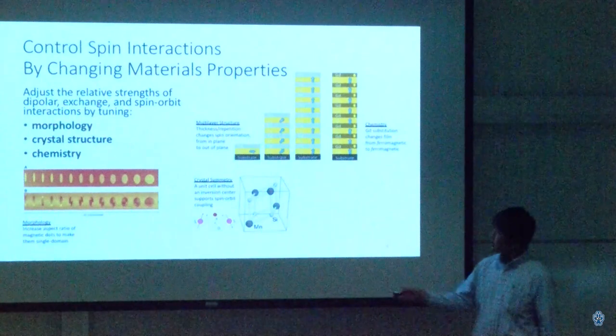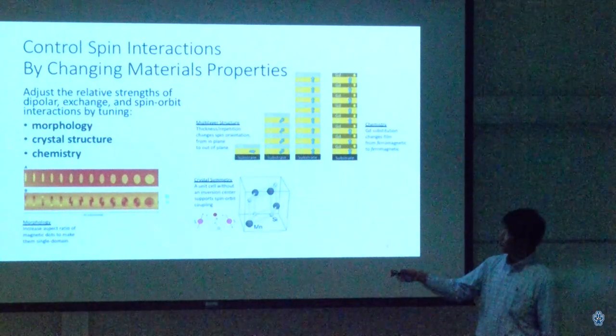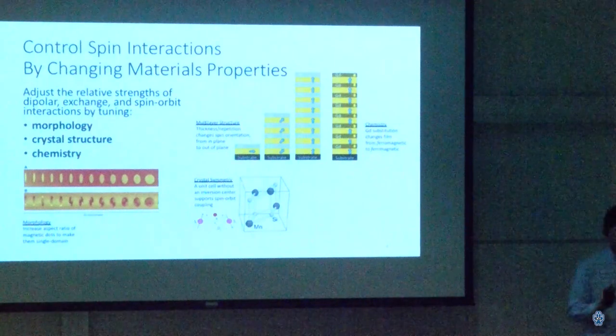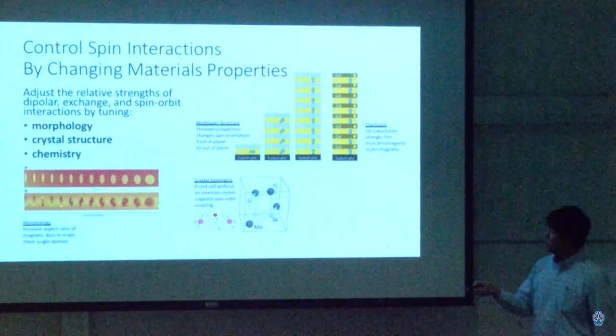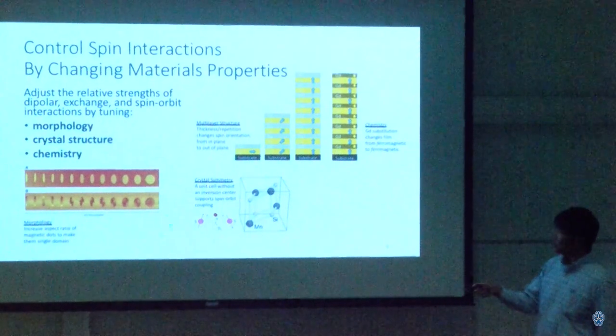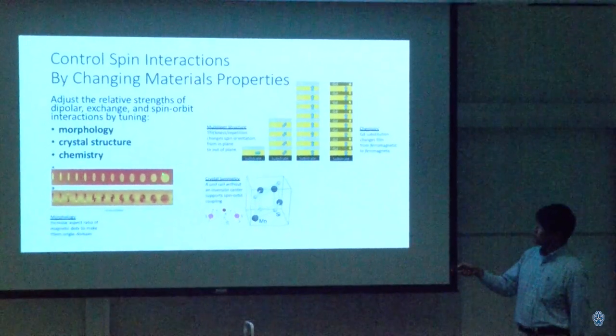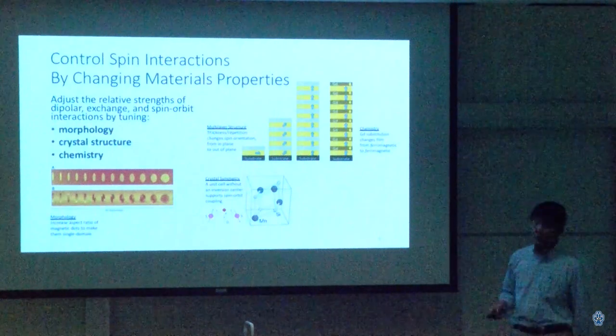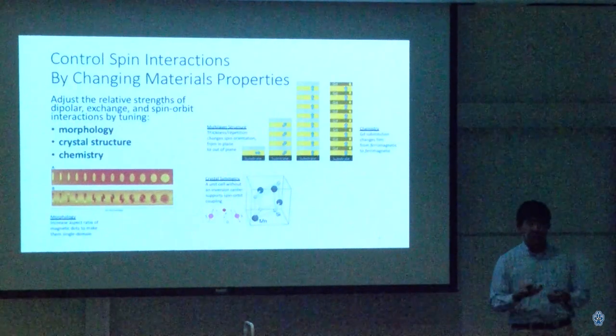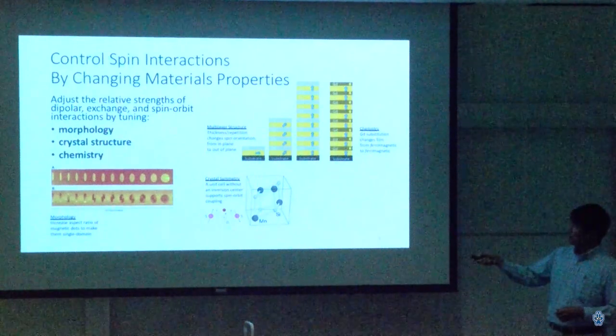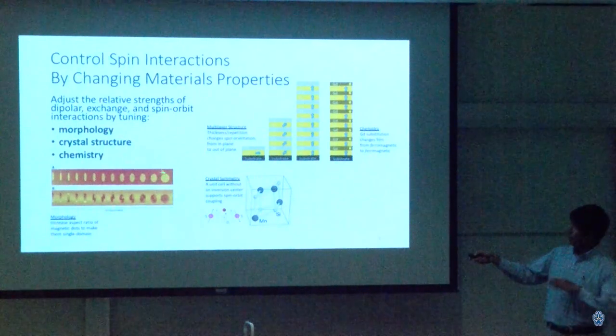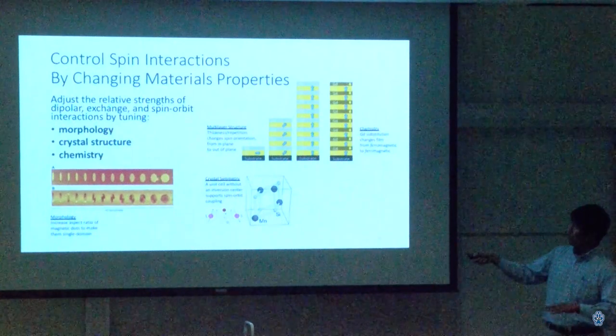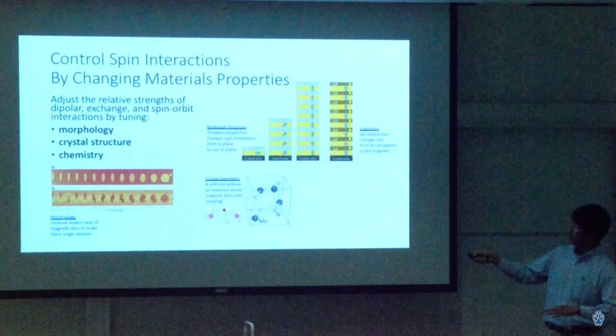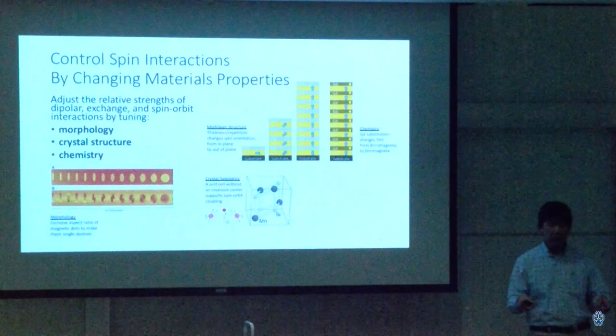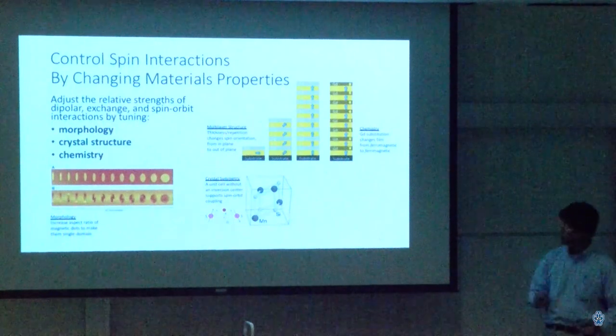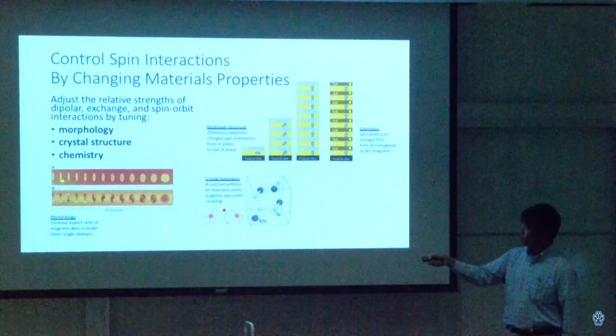So on the bottom left is an example of how to change the morphology and thereby change the dipolar interaction. This is from a paper, the citation will show up in a second, in which researchers created a film of a magnetic material called permalloy, an alloy of nickel and iron. And the idea is that they created different shapes. The film segment on the right has the same aspect ratio as a pancake, it's circular and very flat. And then going from right to left, it turns more into a candy bar.